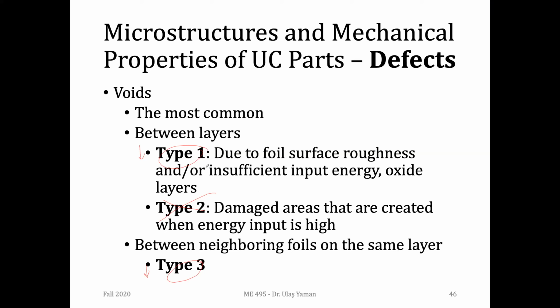Yeah, these are all not related to the parameters we discussed. They depend on the quality of foils you have and the oxidation you have on the foil, so we cannot easily control them. But once you have sufficient input energy, you may decrease, but you cannot totally eliminate it. And regarding the third one, if your foils again are, let's say, tilted a little bit, you may have gaps between the adjacent foils. So again, it's quite difficult to eliminate the type 3 defects totally.